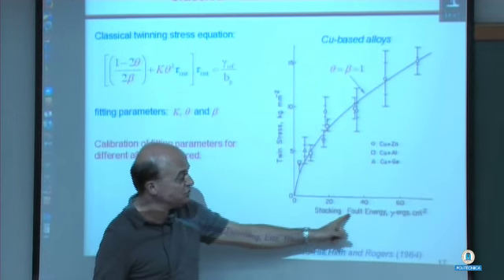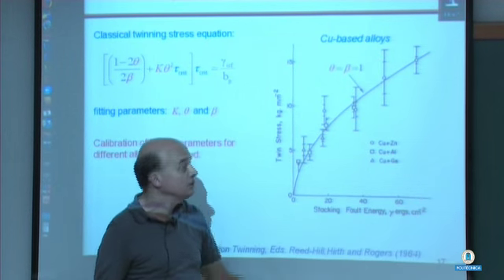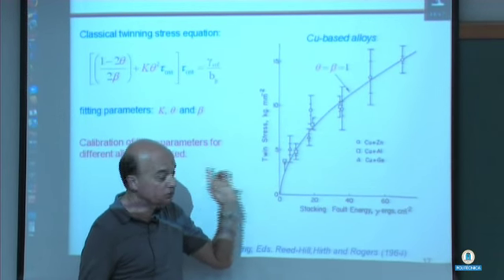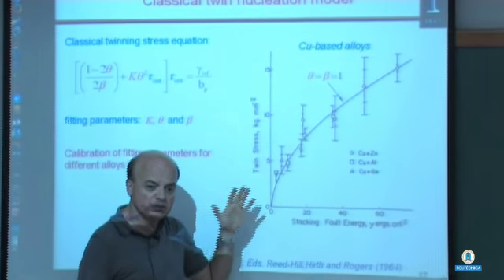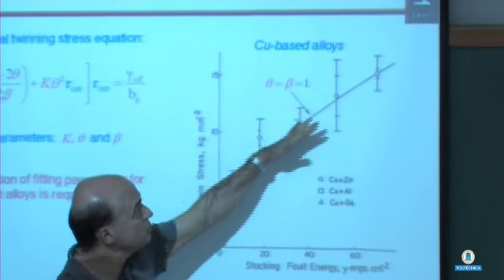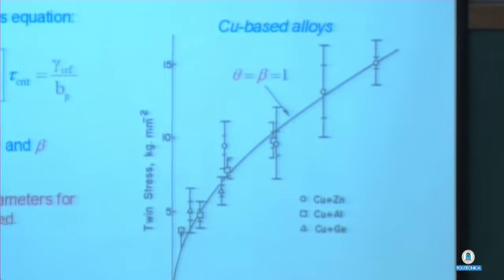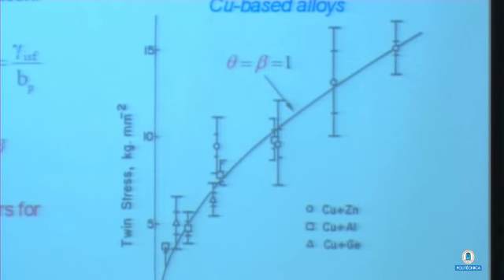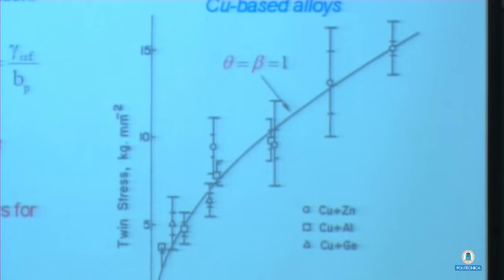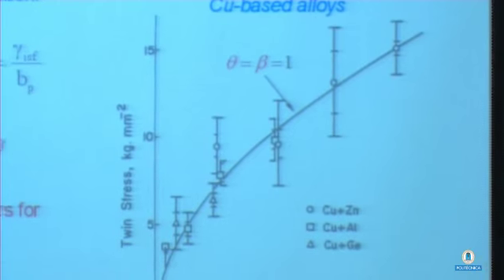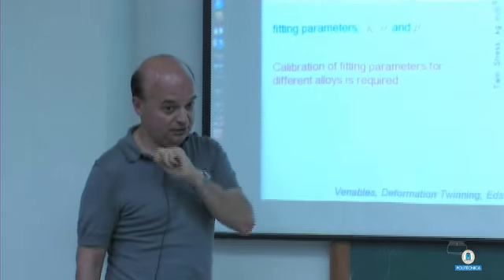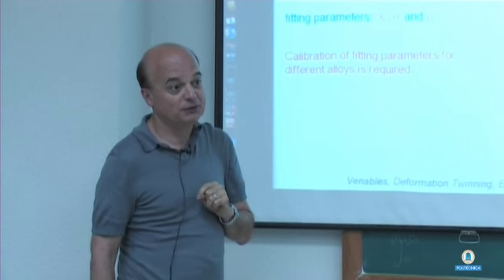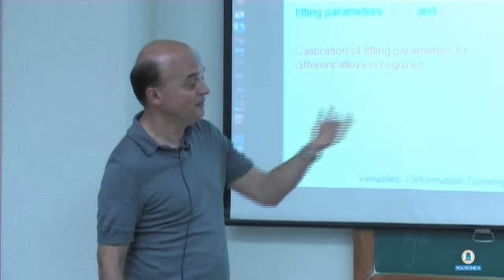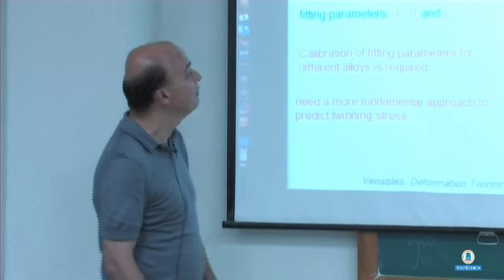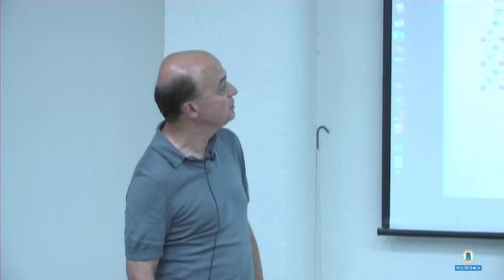And you could see as the stacking fault energy goes up, this model predicts the correct trend. The twin stress goes up. But it says that the twin stress is only a function of gamma ISF. But I just said that the entire energy curve should play a major role, not only the stable value. We need a more fundamental approach to predict twinning stress.